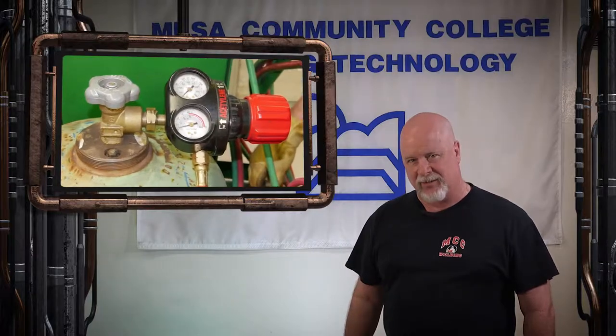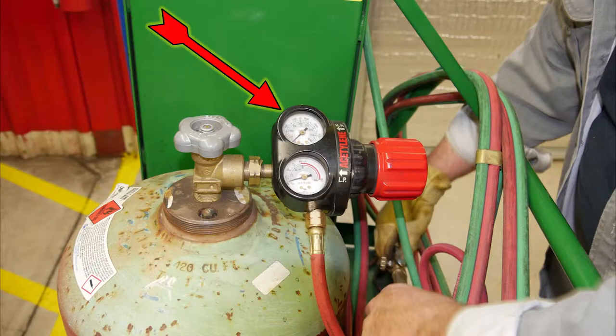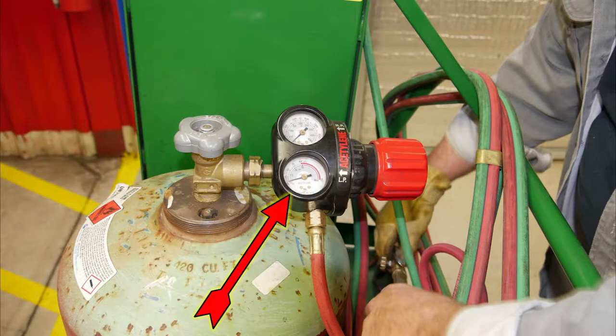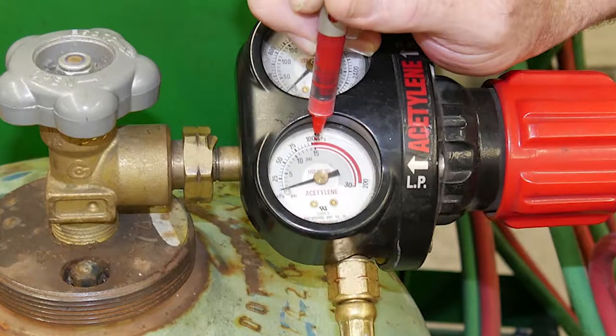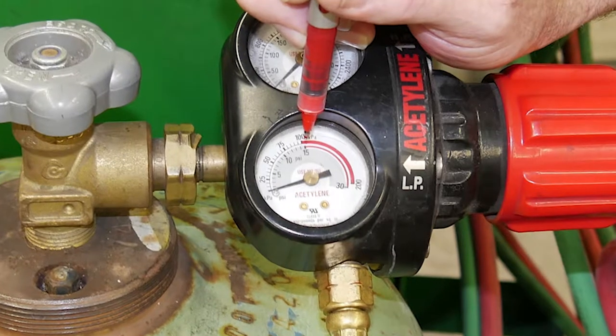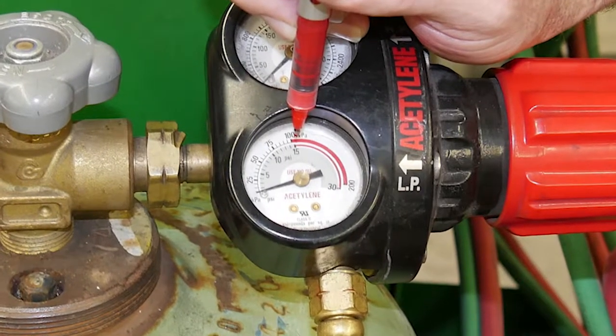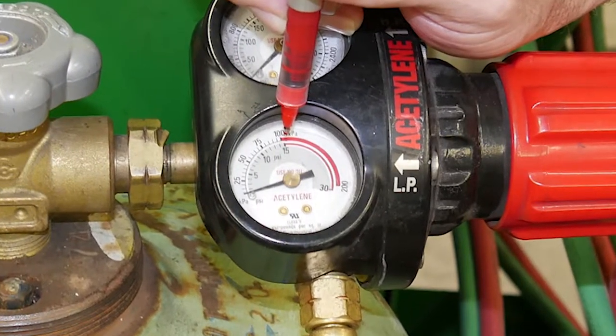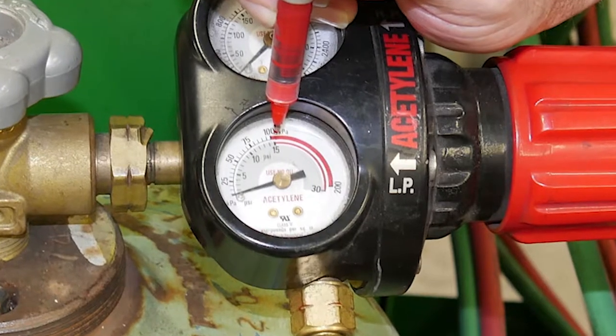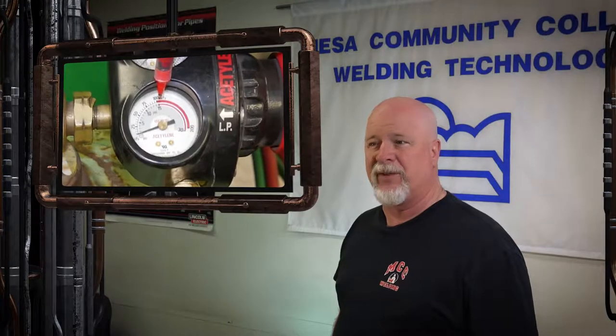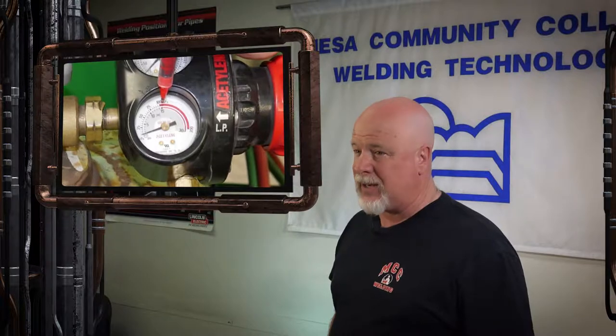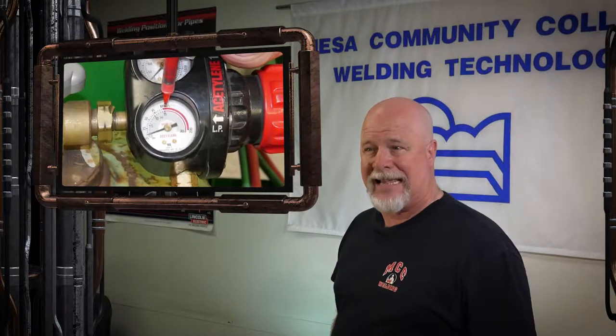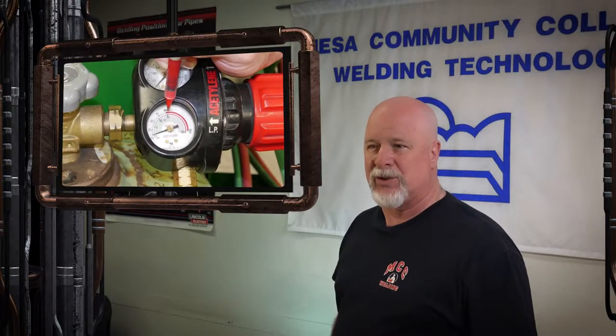Both oxygen and acetylene regulators have two gauges, a cylinder pressure gauge that indicates cylinder pressure and a line pressure gauge that indicates the line pressure that it has been adjusted to. The line pressure gauge on your acetylene regulator has a range outlined in red that is a critical zone which should never be used. When acetylene is discharged above 15 psi, cavitation may occur inside the tank, causing heat in the cylinder to increase, resulting in a possible explosion.